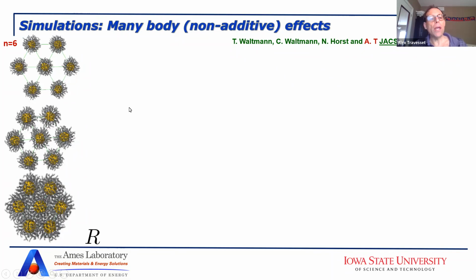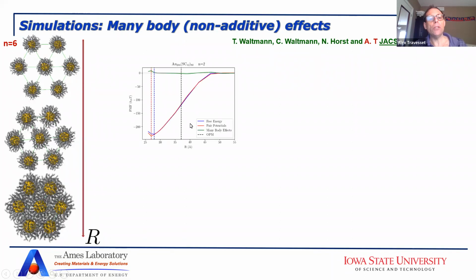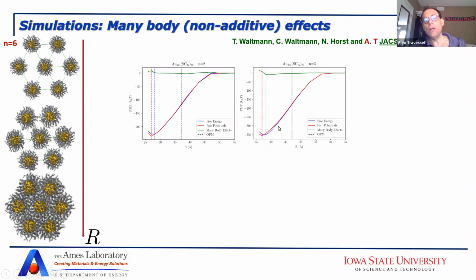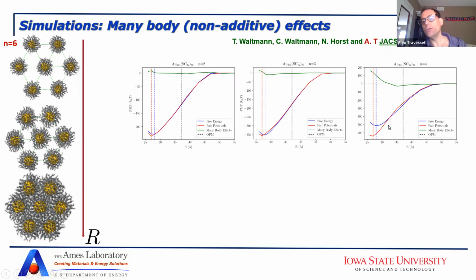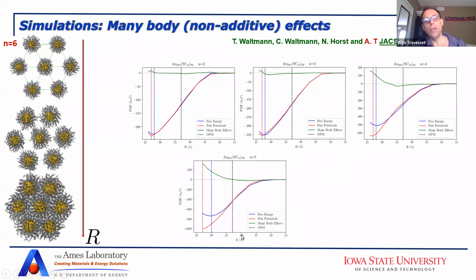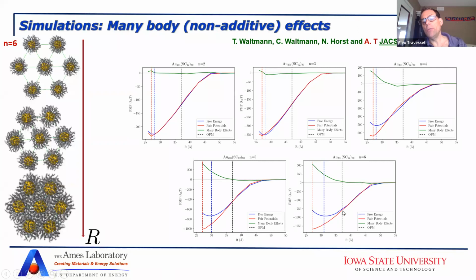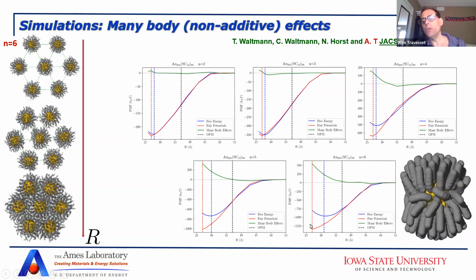So you start with n equal 2, so that would be just 1 particle at the center and 2 at the end. You get something like that, and you see that the sum of the potentials is basically the same as the free energy. When you put 3, the situation is close, but you start seeing some differences. With 4, you start seeing significant differences. With 5, you start seeing bigger differences, and with 6, the difference becomes even more important.